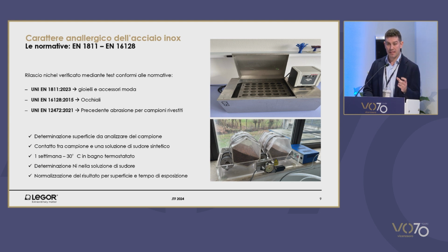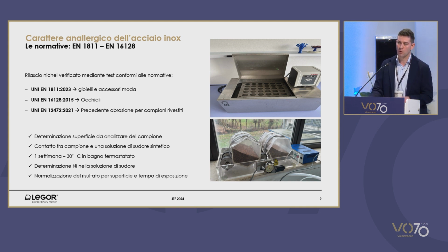And to measure the nickel release, artificial sweat is used on the surface. A test is performed between the object to be analyzed, the surface to be analyzed, and artificial sweat solution. With EN 1811, the object is totally included in the solution. In the case of eyewear, there's a band which is containing artificial sweat, which is connected to the item of eyewear. The test lasts for a week. The temperature is of some 30 degrees. At the end of the test, the nickel presence is detected.